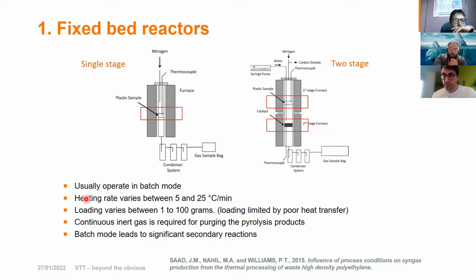The heating rate for this system can vary between 5 to 25 degrees centigrade per minute. And the loading, which means how much plastic you put in, depends on the type of the system, but it's still very small, 1 to 100 grams. A continuous inert gas is required for purging the pyrolysis product. So you need to have some sort of driving carrier gas that takes the pyrolysis gas away from the reactor into the condensing system.